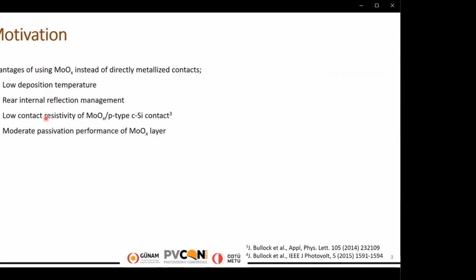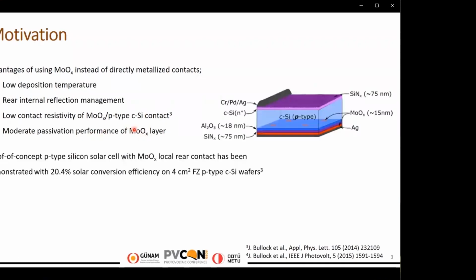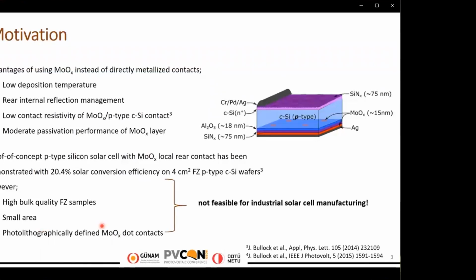The other advantage is the low contact resistivity of the molybdenum oxide/P-type crystalline silicon contact, with moderate passivation performance of the molybdenum oxide layer. Only one work has been reported until now where hole collecting molybdenum oxide is utilized in PERC, achieving an efficiency over 20%. However, high bulk quality float zone wafers were utilized on a small area, 4 centimeters squared, and the molybdenum oxide/silver rear dot contacts are defined by photolithography, which is not compatible with standard industrial cell processing.